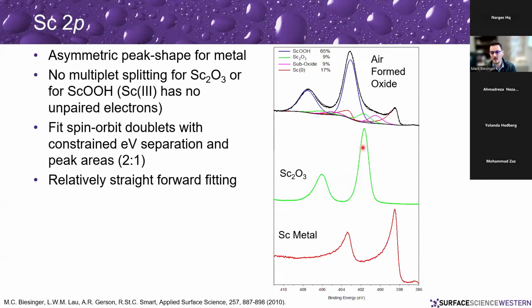So we're going to constrain the peak positions between the 3/2 and the 1/2 peak. We're going to constrain the positions of the metal and also a defined peak shape for the asymmetry. And then we can plug that into a model that curve fits these unknown samples, and we can pull out how much scandium metal we have, how much scandium oxide we have, how much oxyhydroxide we have at different binding energies. It's a relatively straightforward fitting with the proper constraints applied.